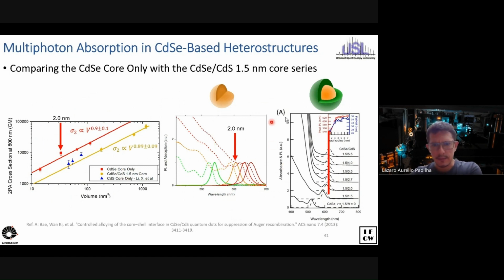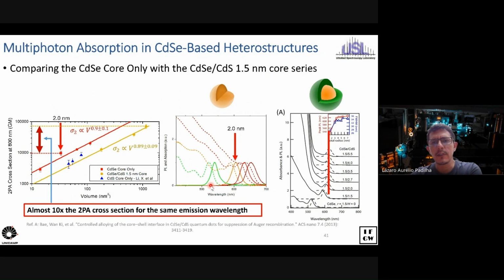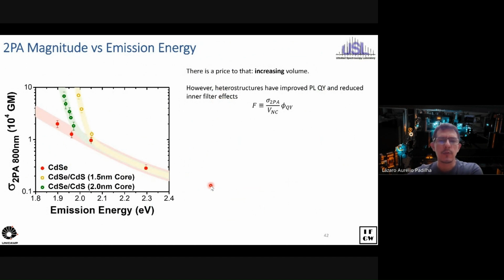In fact, if you take this sample here with a 2 nanometer core, it emits at around 600 nanometer, which is about the same emission as the quasi-type 2 sample with a 1.5 nanometer core. But if you compare the two-photon absorption cross-section for the two, you get about one order of magnitude enhancement. So we actually learned a way to decouple two-photon absorption cross-section and emission wavelength, and we can get an order of magnitude change in the cross-section by simply playing with the heterostructure. We can see this in a better way if we plot the two-photon absorption cross-section as a function of the emission wavelength or emission energy here. You see for the core-only, it really moves the emission energy, while for the heterostructure, that's not the case.